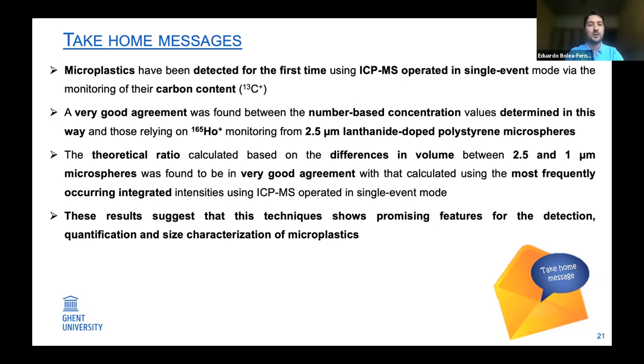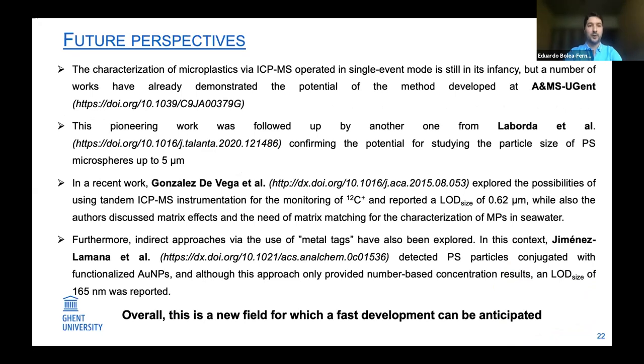The theoretical ratio that we calculated based on the differences in volume between the two polymeric microspheres was found to be in very good agreement with that calculated using the most frequently occurring integrated intensities using ICP-MS operated in single event mode. And these results basically suggest that this technique shows promising features for the detection, quantification, and size characterization of microplastics. There are also some future perspectives for the development of this method.